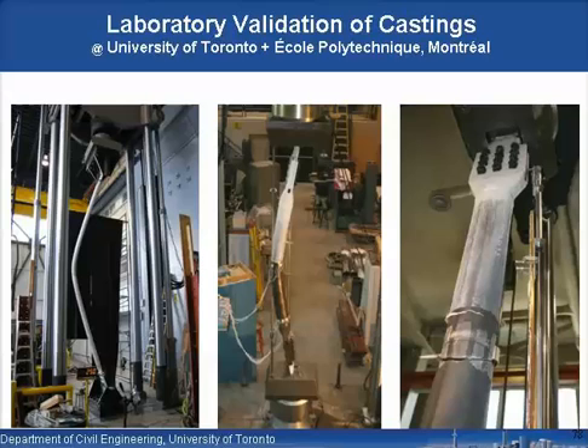These have gone through laboratory validation and testing as well. I think we had this picture on the left before, but this shows the huge amounts of displacements that these tubes can go through if you keep the tube relatively thick and stocky, keep the overall KL over R long, up around 100, but certainly over 70,